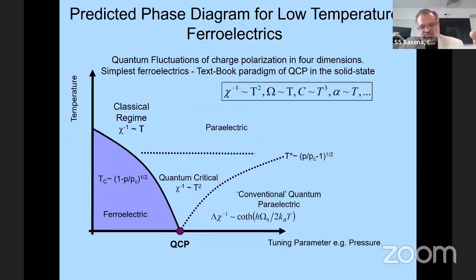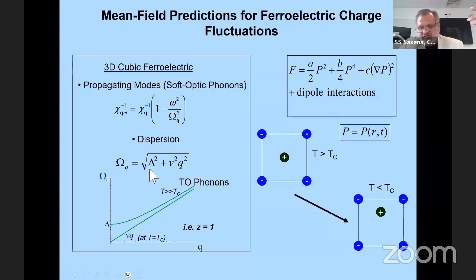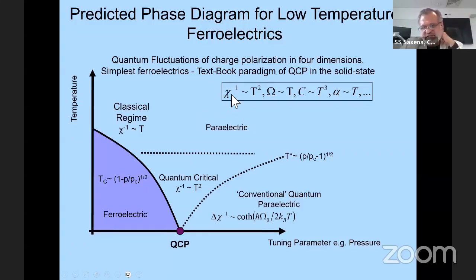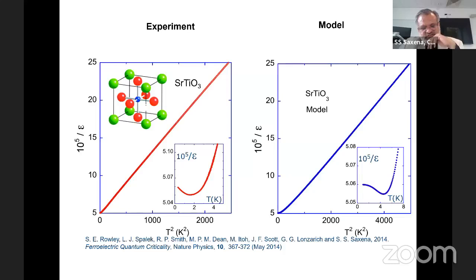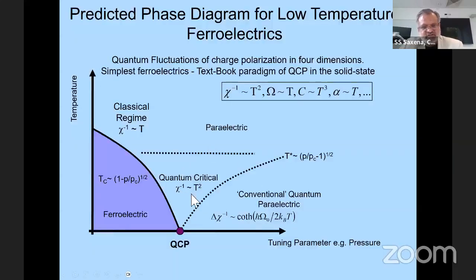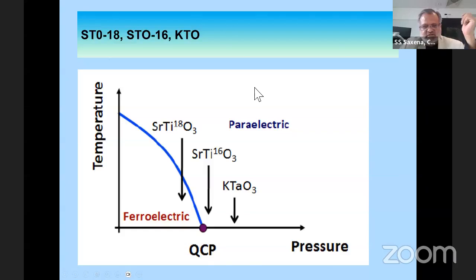So just using the previous picture, we can solve for free energy, and we can look for the measurable properties, say susceptibility, thermal conductivity, heat capacity, and thermal expansion. We will focus almost entirely on susceptibility measurements initially, but it also gives you a sense of the phase diagram. So we're sitting here in the phase diagram. For strontium titanate, this is where it sits naturally. And if you look through experiments, we had to actually build low temperature dielectric measurements. It took a long time, but we were successful. You can actually measure epsilon, the dielectric constant, and you find that it fits a T-squared, which is the quantum critical power law in the story, which is given here.